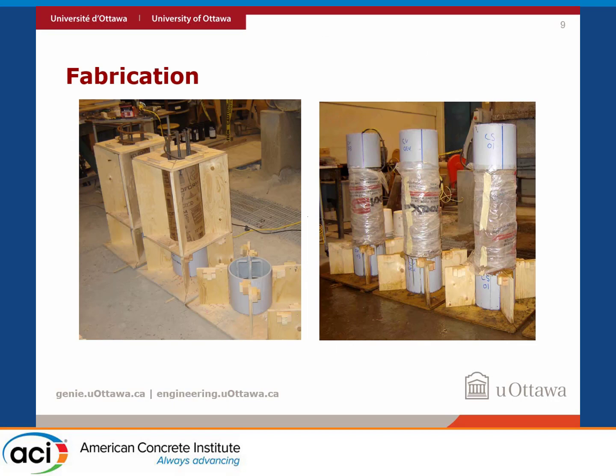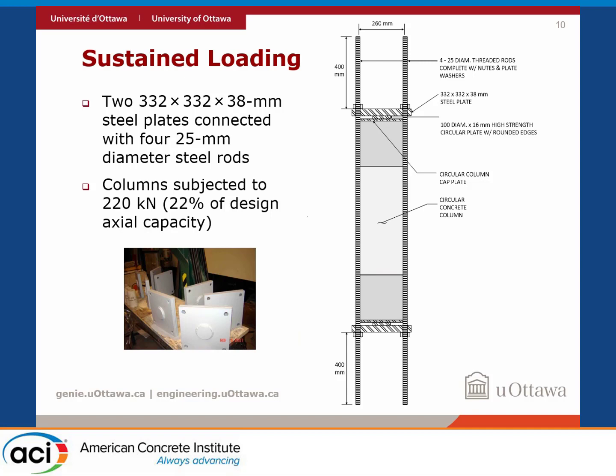So here you have a look at the specimens. We placed steel caps at the bottom and top of the specimens because we wanted to induce the damage in the middle of the column. Those steel caps were coated with zinc paint so they wouldn't corrode. We cured the specimens with moist burlaps and wrapping plastics for 14 days to make sure that they had proper curing. And once they were cured, we subjected them to sustained loading.